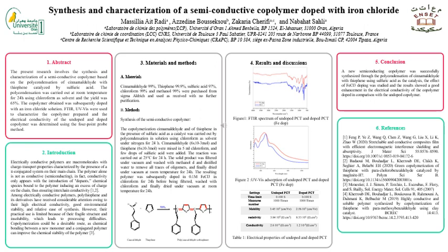Electrically conductive polymers are macromolecules with charge transport properties, characterized by the presence of a π-conjugated system on their main chain. The polymer alone is not as conductive. In fact, conductivity only appears with the introduction of dopants, chemical species bound to the polymer inducing an excess of charge on the chain, thus ensuring interchain conductivity.